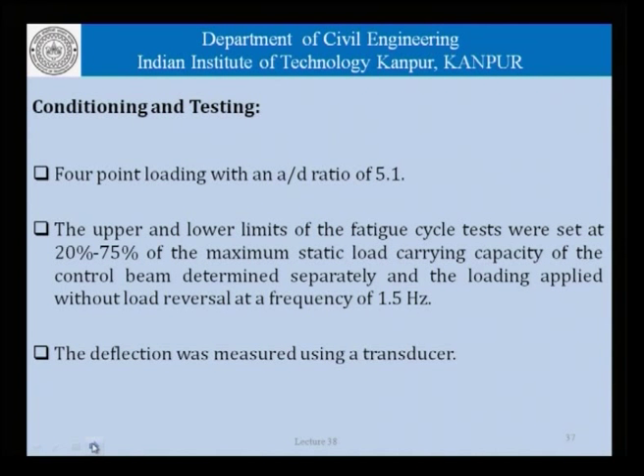4-point loading test was carried out using an a by d ratio of 5.1. The upper and lower limits of fatigue cycle test were set at 20 to 75% of the maximum static load, and the frequency of load without load reversal is 1.5 hertz. So, this really describes the fatigue test.